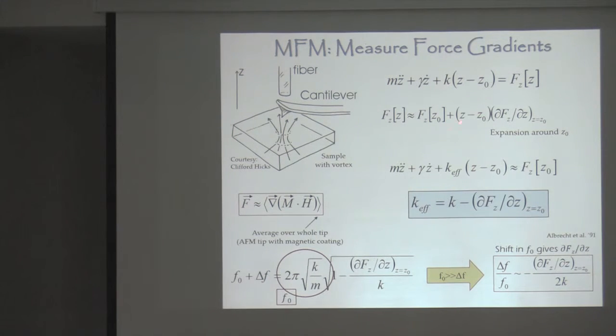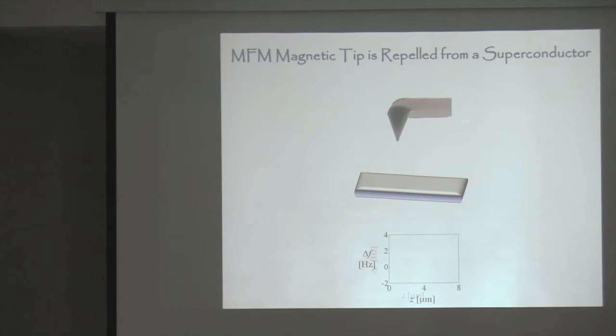This is the equation of motion. I'm not going to go through this, but in the end, what we do is we have this cantilever. It has a resonant frequency. If it were in free space, it would be the square root of k over m. But then this resonant frequency shifts by an amount that's proportional to the local gradient of the force. So that's what we measure. And there are various reasons for doing this, for measuring this, and not just how much the cantilever bends directly.